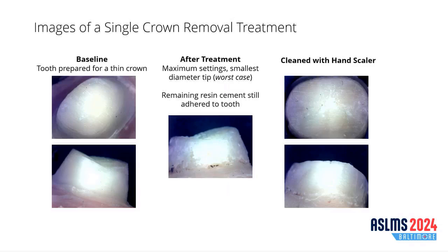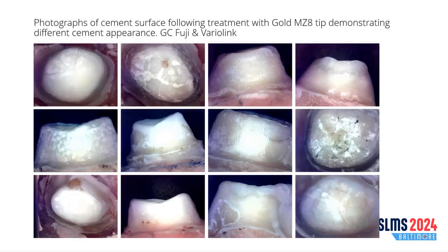Here's another set of images of the tooth baseline right after crown removal. This is our worst case, meaning the highest fluence settings with the smallest diameter tip, maximum energy settings, and a thin crown. You can see the way the laser acts is it penetrates all the way through the ceramic or glass restoration, and it affects the cement underneath. It starts to ablate it. So you can see a little bit of ablation there. We do not want to ablate all the way through the cement and start to ablate the dentin. And after cleaning with a hand scaler, that's the appearance of the tooth.